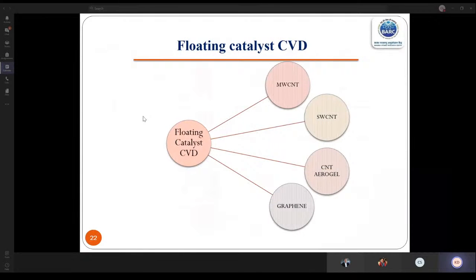So far I have talked about the fluidized bed technique, where we require some substrate material on which the carbon nanotube grows. There is another technique called floating catalyst chemical vapor deposition. CVD means chemical vapor deposition. We can prepare multi-wall carbon nanotube, single wall carbon nanotube, graphene, as well as CNT aerogel. And this floating catalyst is typically used for CNT aerogel, which I'll show, what is CNT aerogel.